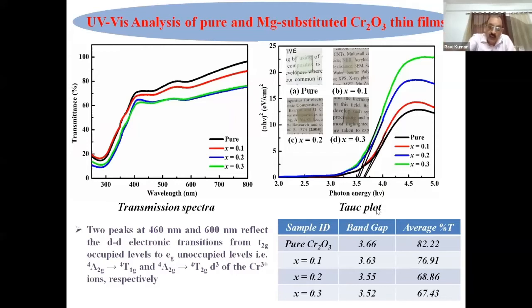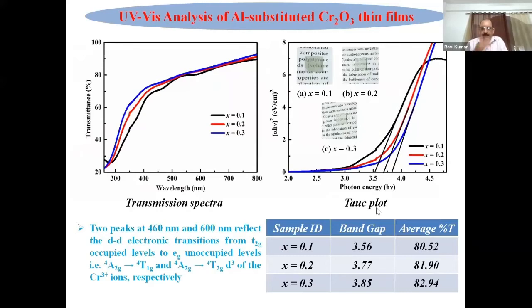And now you again use the Tauc plot, and those Tauc plots will give you the band gap. And you see, as the magnesium is being substituted into the system, the band gap is varying. Now, if you look at the case of aluminium, here the things are reverse. Higher the aluminium substitution, more is the transparency. It means that the band gap is increasing.